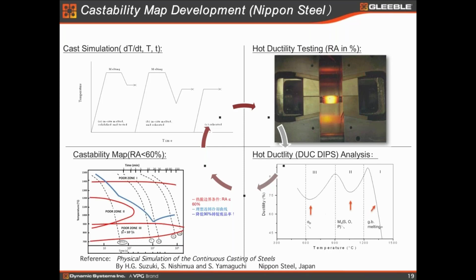And for this example, it's very easy now, but they found that low ductility region 1 is near the NST, the nil strength temperature. So the ductility is very low, and if the thermal stress or mechanical stress in the casting exceeds the stress that the material can stand, you will have cracks. That is why smooth, very great alignment of the casting rolls is very important. Okay, but that's not enough, because the thermal stress generated by thermal gradient is very important.